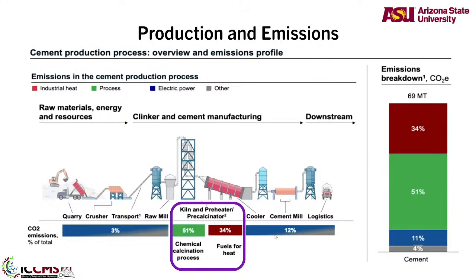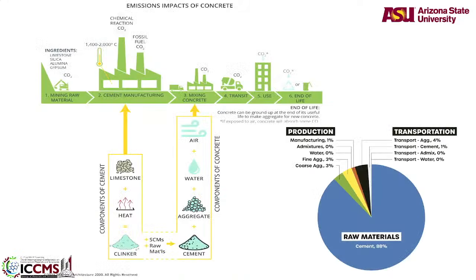Now, the first question is, chemistry is arresting us right there. Calcium carbonate, to become calcium oxide, you have to take carbon dioxide out. There is no other way, right? You are stuck with chemistry there. Now, okay, then you say, I don't want calcium carbonate. I can use calcium silicate. You end up with another problem. We don't have as much calcium silicate as calcium carbonate, and calcium silicate transformation to calcium oxide to take the stable silica out is an even bigger problem. You have to do other methods, not just heating. So now you end up with difficulty in processes, you end up with having to have that extra CO2. So, and then again, that's a process that we talked about.